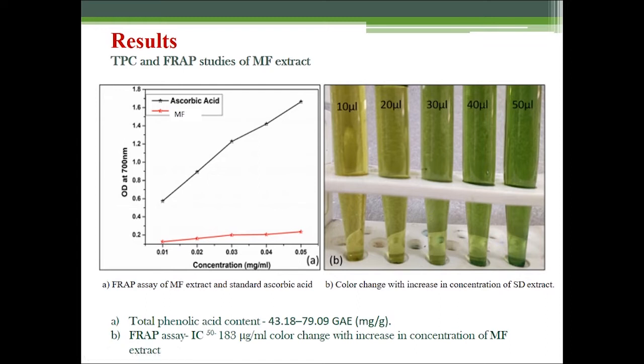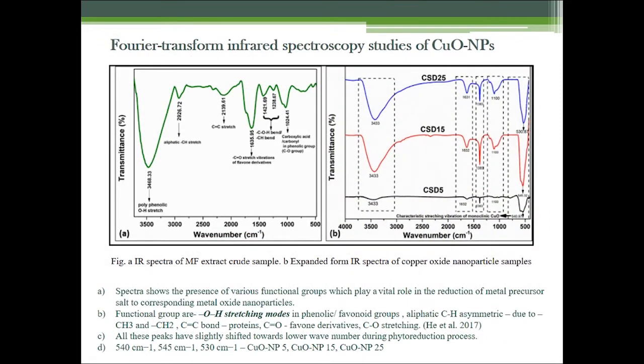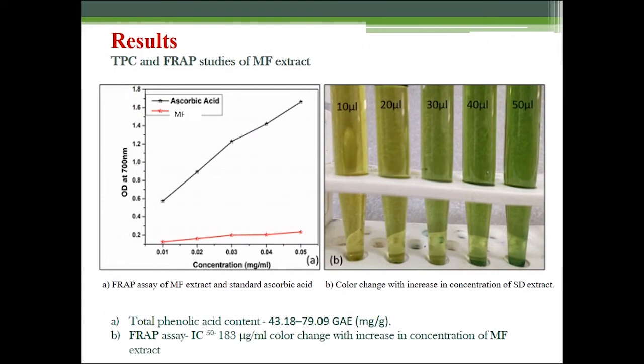With the increase in the concentration of plant extract, the activity exhibited by the plant is also increasing. Coming to the FTIR analysis, we have found that polyphenol components were present, and the antioxidant capacity of the plant extract was determined and the IC50 value was found to be 183 microgram per ml. So with this result, we have selected the plant extract for the synthesis of nanoparticles.